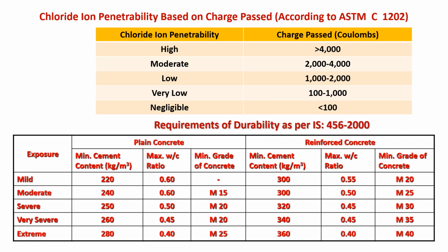If you closely observe, this is the table from ASTM C1202. You see this classification: high, moderate, low, very low, negligible. And our classification is almost the same: mild, moderate, severe, very severe, and extreme. There are 5 classifications here and 5 classifications there. High means you are allowing a high amount of chlorides, equivalent to mild. Then the same name is given for moderate, and severe corresponds to low, like that. There is a similarity between this table and this table. Then why can't we adapt this system here, so that instead of these prescriptive parameters, we can adopt the performance-based parameter?